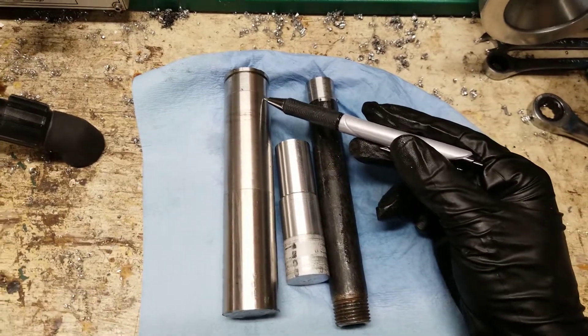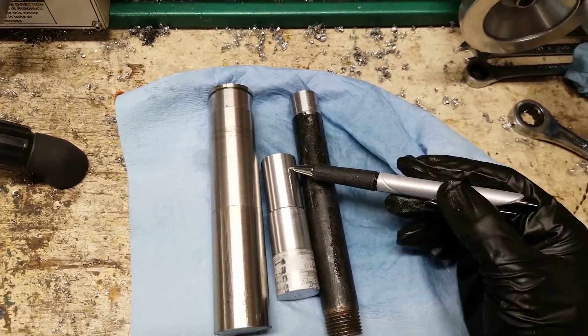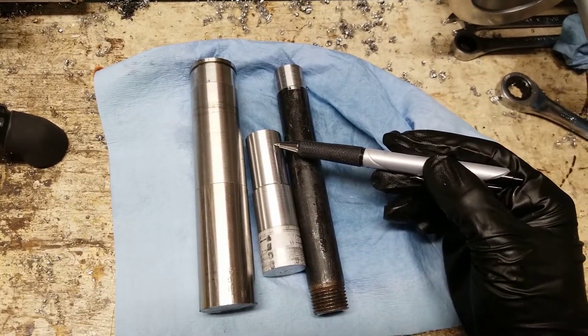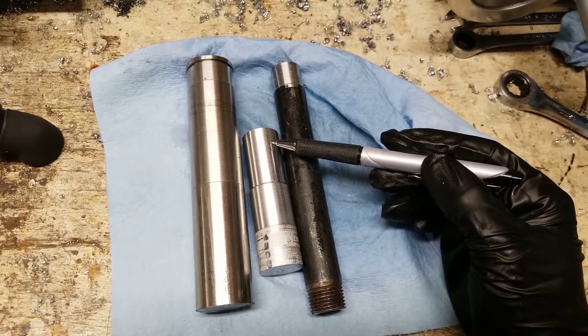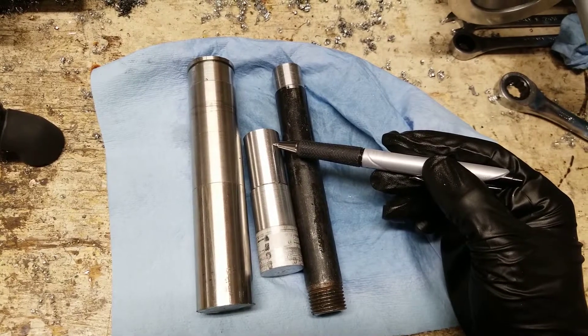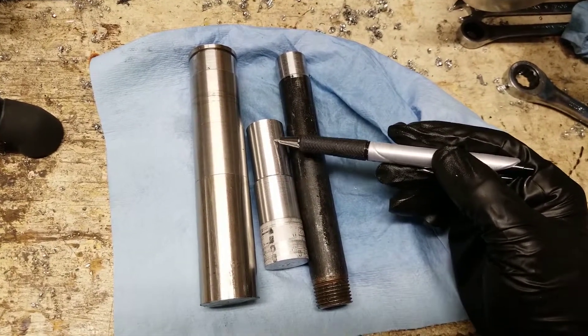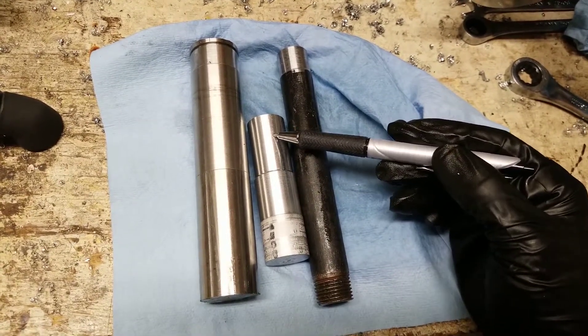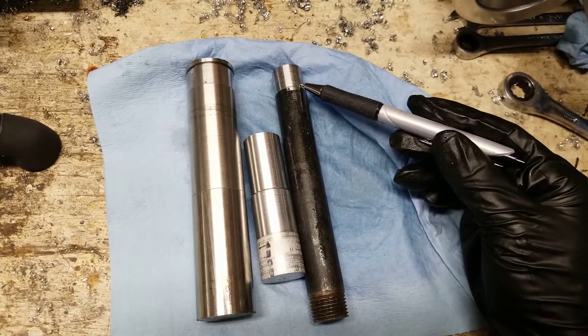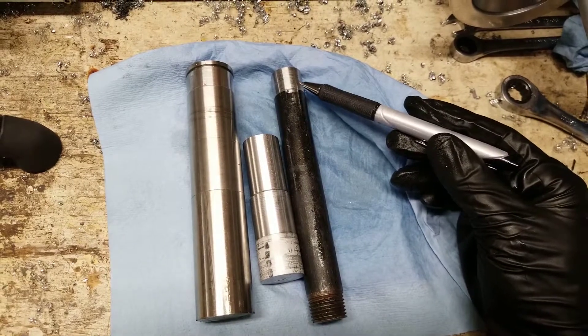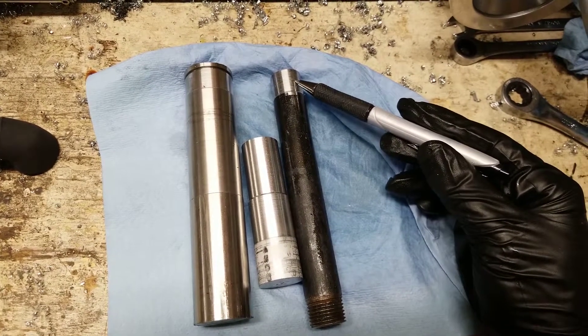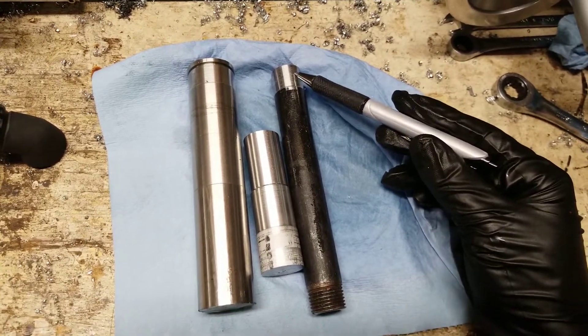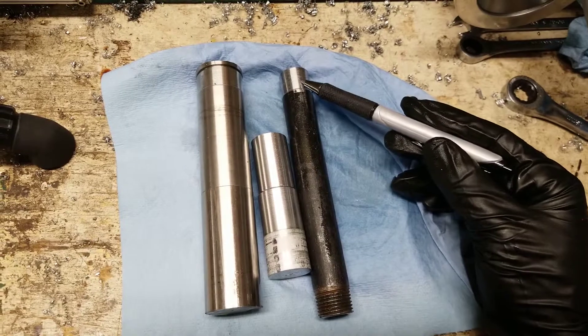The aluminum had very small, short chips that would break off after just half an inch or so. The surface finish was shinier than on the mild steel. For the mild steel, the chips were incredibly small, and the surface finish was the worst out of the three.